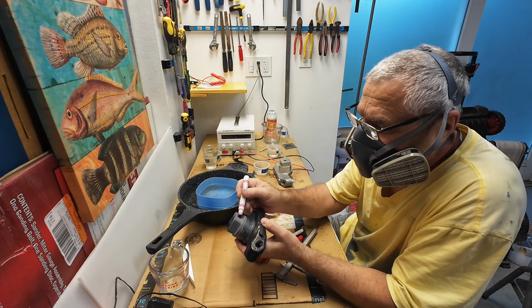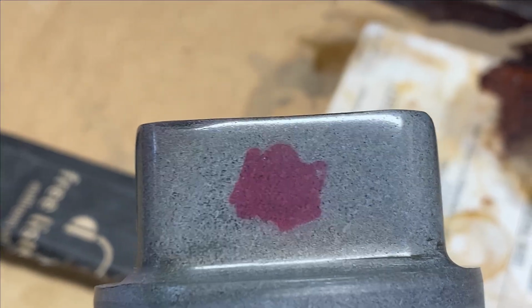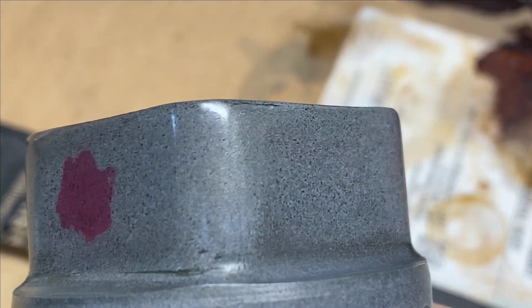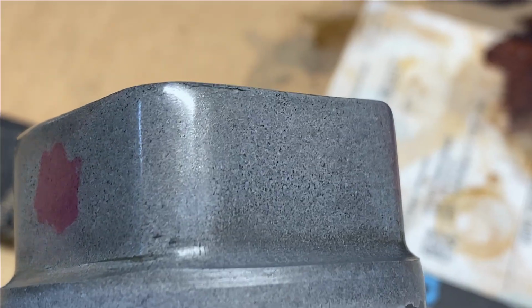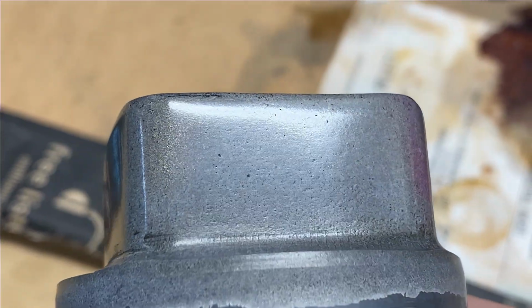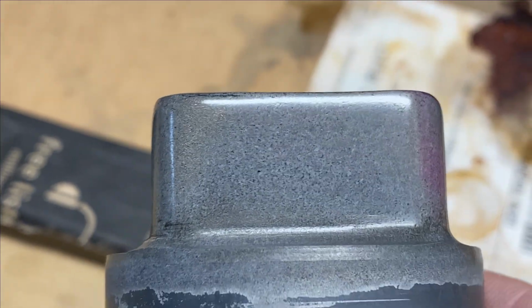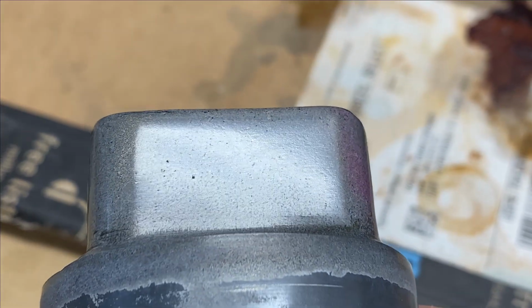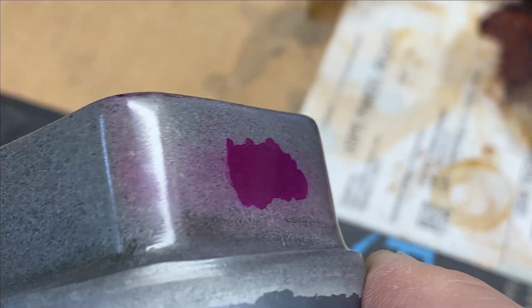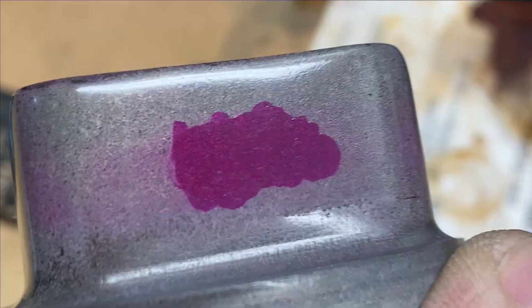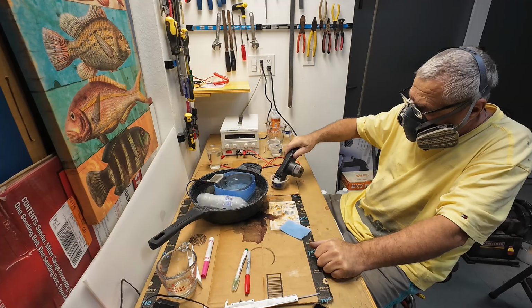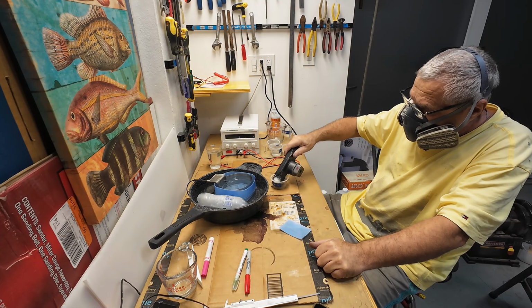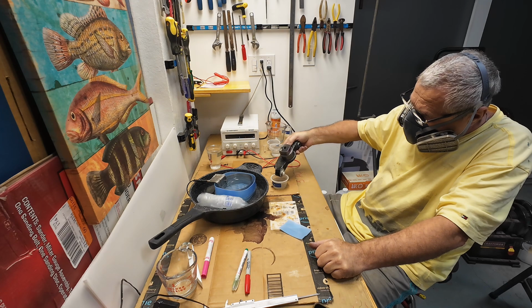The marker leaves a trace on the surface that doesn't rub off during polishing. This indicates the dye is absorbed into the oxide layer. It turns out that my cooling was insufficient, and the oxide layer could have been made even more durable. I should lower the process temperature a little. It's a pity I don't live in Alaska.